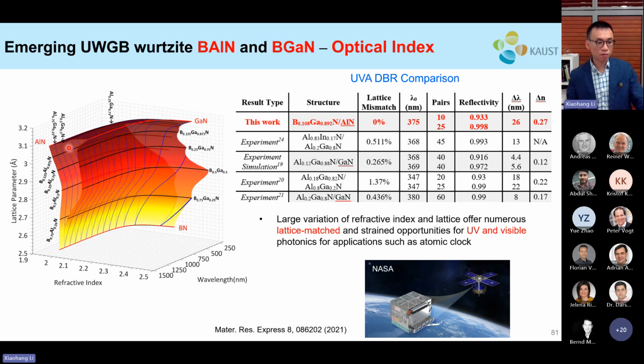So this is a three-dimensional image that we calculated based on DFT. Here you have the lattice constant, you have boron nitride, aluminum nitride and GaN, and this is the refractive index, and this is the wavelength corresponding to the band gap of those materials. If you look at the AlGaN layer, whenever you want a larger delta n, you have a larger delta a as well, a being the lattice constant. But when you add boron into the game, if you draw a horizontal line from left to right, you get a lattice matched heterojunction with a large delta n.